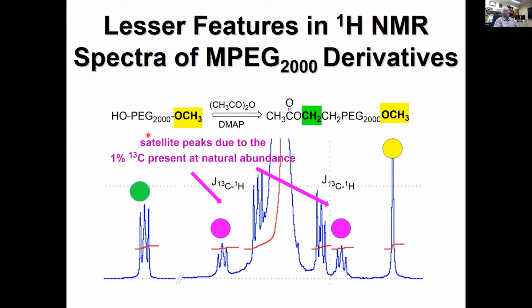It shows that if you have something like a PEG 2000 with a methoxy group, you'll see this methoxy peak right here, off scale—that's the PEG group. If you modify this to make an ester on one end while keeping the methoxy on the other, you'll see a new peak corresponding to the CH2 of the ester. Further upfield, not shown here, you'll also see the CH3 group of the ester.